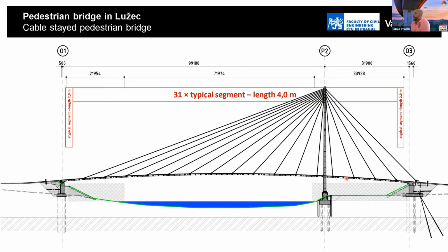About the basic idea of the superstructure, it is realized by 31 typical segments. The length of the typical segment is 4 meters. On the side, a typical segment with a length of 2 meters was used, and also a special part you can see here, and in this area, the part of the superstructure was realized by casting in situ.